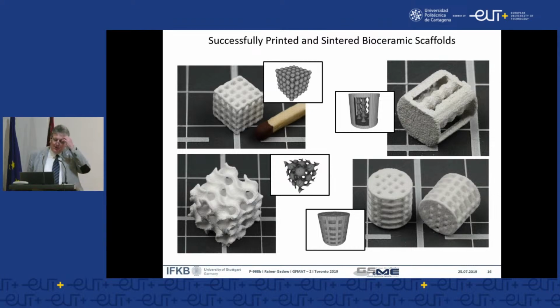So there is a variation of the geometry and the porosity depending on the material properties and the printability, and this complex structure was achieved by the same principal processing. The design is coming from colleagues from the Vienna Technical University and the Faculty of Medicine. They want these structures because they have a much higher compressive strength. That means the learning by doing is also to learn from colleagues in neighboring disciplines which is the most appropriate